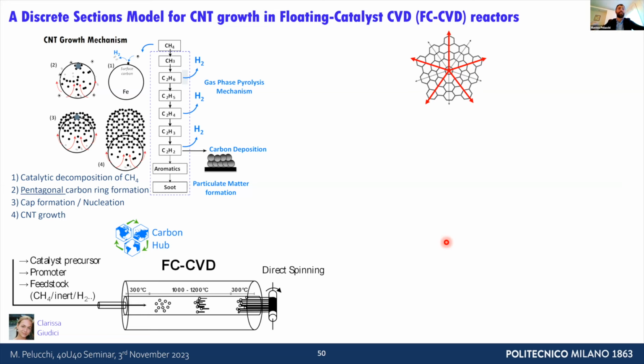But in reality, the quality of a nanotube is defined by the aspect ratio, the length over the diameter. And the diameter, when the catalyst is sprayed in, is strictly dependent on the diameter of the catalyst. So you'll have a distribution of diameters, and therefore a distribution of aspect ratios and diameters of the carbon nanotubes.